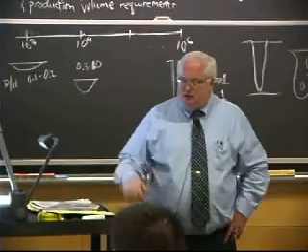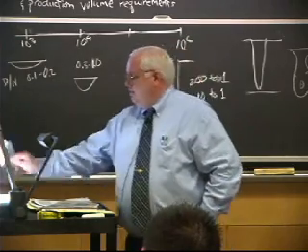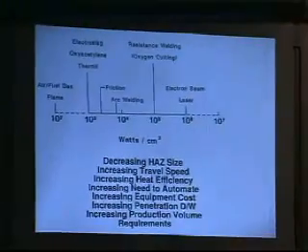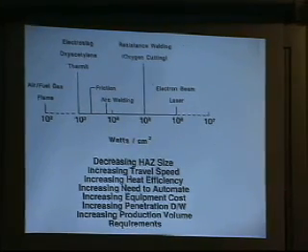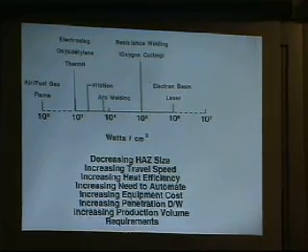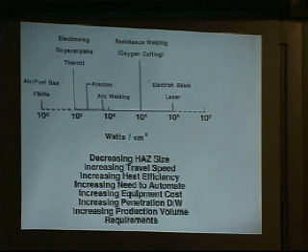And actually the third one is essentially these high voltage, these megavolt electron beams. I'll put this thing back up. Remember we said that at 10 to the 6 watts per square centimeter, you have such a high heat intensity, you just vaporize the surface. And if you go above 10 to the 6, you vaporize it so quickly the stuff just starts spewing off as a vapor, and you drill a hole through the part.